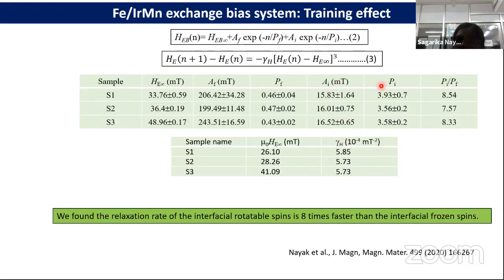However, the relaxation rate of rotatable spins is higher than the relaxation rate of frozen spins, and we found that the interfacial rotatable spins relax 8 times faster than frozen spins. Also, from this configuration we found a very low relaxation rate, of the order of 10 to the minus 4 value of gamma h. Gamma h basically describes the relaxation in this model.